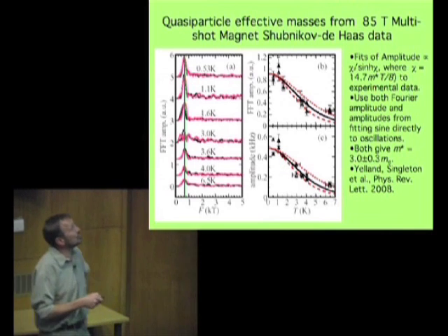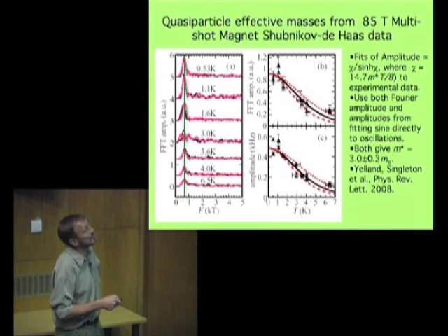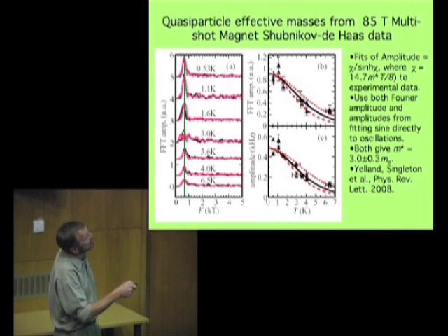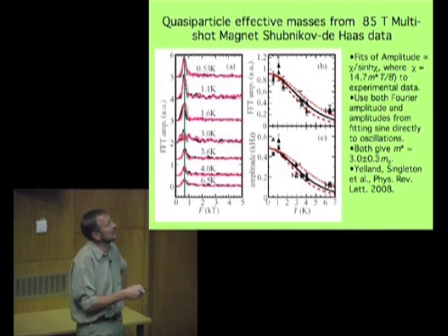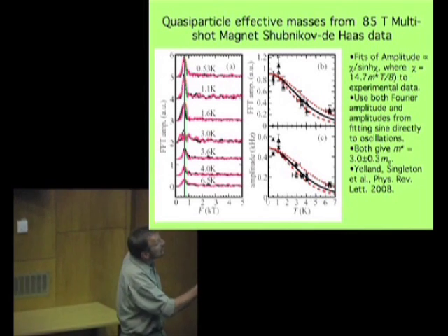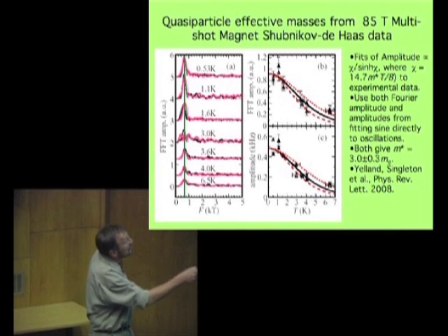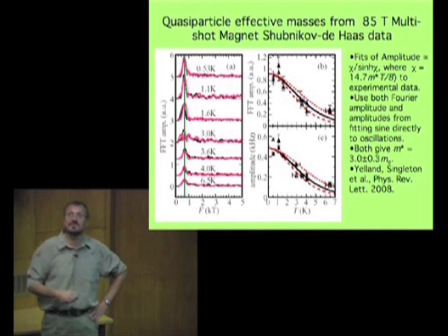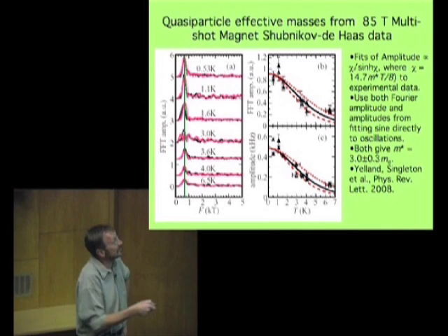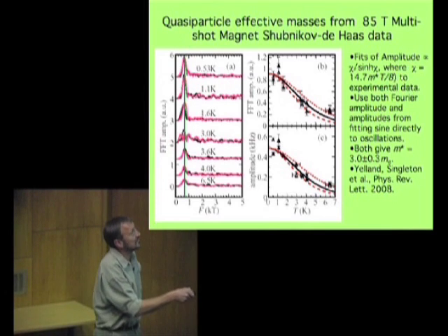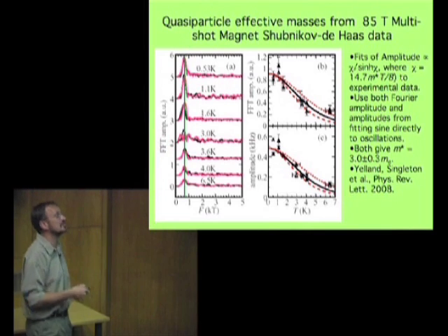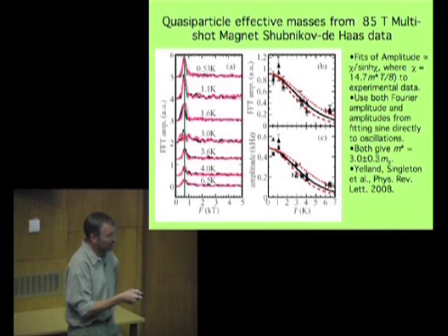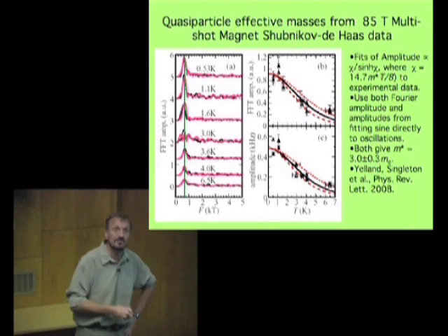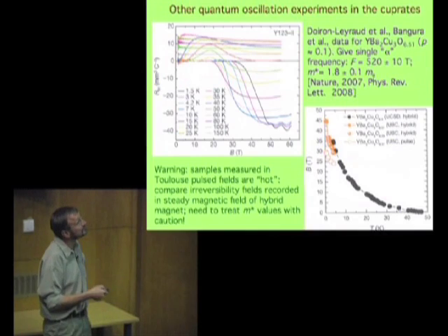Anyway, there are several different ways of evaluating the temperature dependence of the oscillations. We can look at a Fourier transform as a function of temperature, which is this thing here plotted out. We can also do a direct fit of a sine function to the oscillations, which is this one, and both of them give the same answer. We have an effective mass which is 3 times the mass of a free electron. So heavy, but not especially heavy.